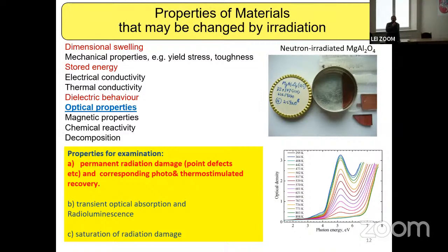For radiation resistant materials, this is, let's say, an additional story. But for classical materials like alkali halides, almost all properties immediately change even after strong X-ray radiation. In our case, because of our place in the Fusion Consortium task, we are interested in permanent radiation damage, so when point defects are created, but we are also interested in the corresponding photo-thermostimulated recovery of radiation damage. Still an open question concerning transient optical absorption and luminescence, because we know even from electron irradiation experiments that most of the point defects which are created by radiation recombine in a very, very short time.